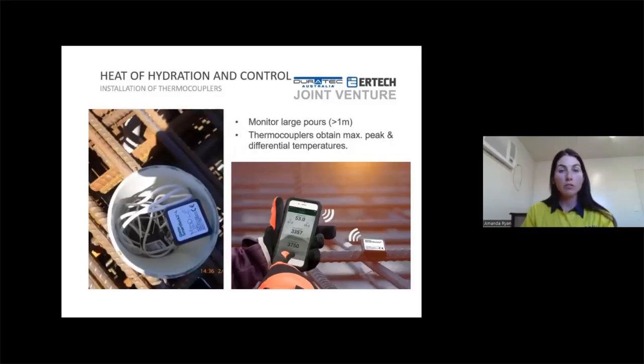So, heat of hydration: how to monitor the heat in the concrete, especially in the larger pours. Within the spec requirement, we were to monitor larger pours, and larger pours were considered where one face of the slab was larger than 1 meter. And to do this, I installed temperature sensors.